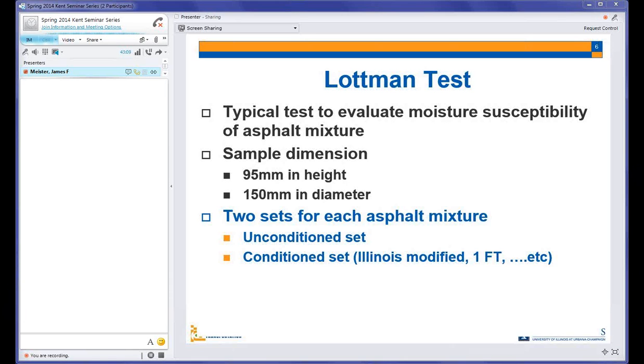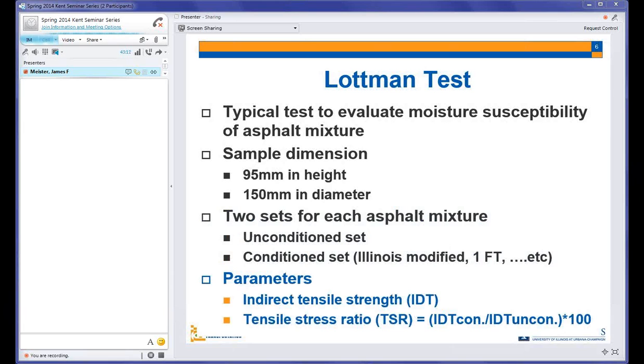Two parameters we take out of this test: the indirect tensile strength, the IDT, and we call it indirect because we apply compressive load, but really what we are focusing on is the tension that we are getting from this test. The second parameter is the tensile stress ratio, which is basically the IDT for the conditioned set relative to the IDT of the unconditioned set.